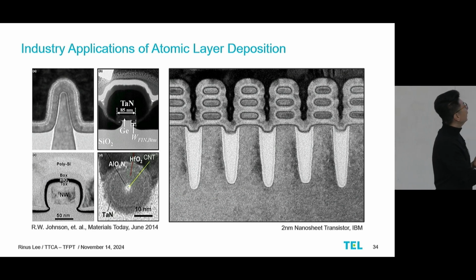And on the right is a device structure by IBM showing the 2 nanometer nanosheet transistor. And you could see once again, these are the nanosheets itself, or the channels. How do you fill these areas between the channels? By using atomic layer deposition, by reacting with the surfaces, you're now able to fill these spaces that wasn't possible with directional deposition.